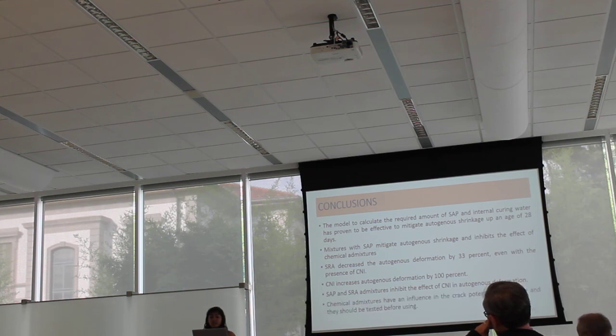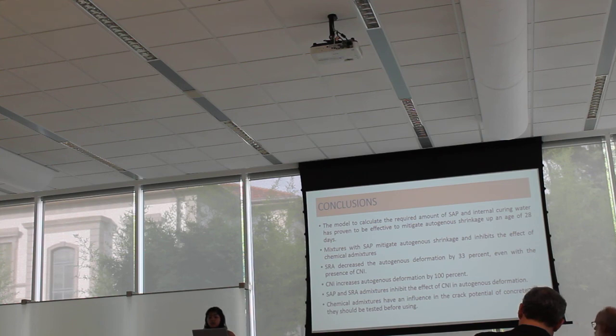Finally, chemical admixtures have an influence on the crack potential of the concrete, and they should be tested before using, because you can have cracks at early age, and this can affect the durability of your high-performance concrete, even if you have high amounts of cement and high amounts of supplementary cementitious materials.